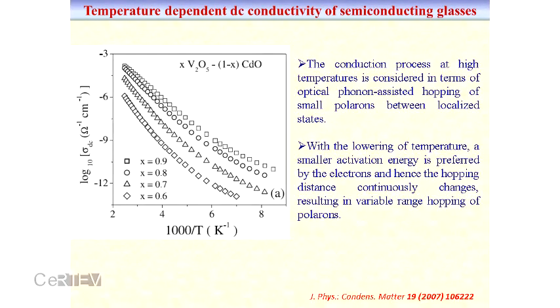Now I will tell you about electronic conduction in materials. Before I go into the details of this, you can see here the plot of the DC conductivity as a function of temperature. This is an Arrhenius plot, for a vanadium oxide modified by cadmium oxide. You can see the slope is changing gradually. At high temperatures the slope is almost constant, but as the temperature is lowered, because this is 1 by T, this side is low temperature. If you define activation energy in a specific temperature range, then you can say that activation energy is changing gradually. For some materials, the activation energy becomes constant, but not in this case.